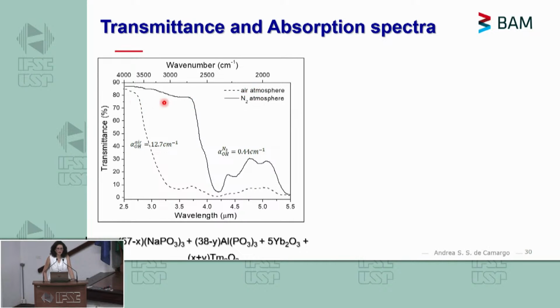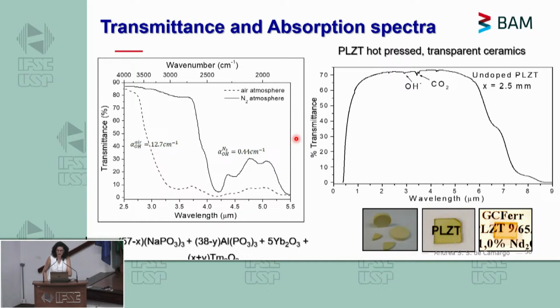You can see a big difference here of the transmission window because in this particular region, water, OH vibrations absorb a lot. So these are definitely glasses that you have to prepare in controlled atmosphere if you want to guarantee that you're going to have extensive transmission in the infrared.